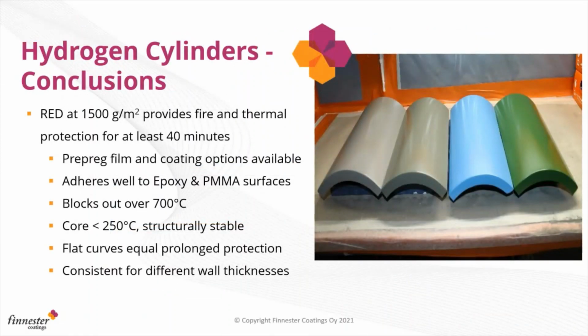In conclusion, at 1500 grams per square meter, it will provide you fire and thermal protection for at least 40 minutes. We have burned 1 hour also, not too much difference. It just consumes too much gas burning it. And it's a pre-preg film or liquid coating, so you can really choose according to your process. It will adhere very well to epoxy and PMMA surfaces. Polyamide will also work nicely. It will block over 700 degrees. The isolation factor is very nice, and the core will stay under 250 C, which means it is easily structurally stable. The curves will flatline, and that is the same thing that you can see, that it gives you prolonged protection. And it's consistent. It doesn't care too much about the wall thickness of the composite.